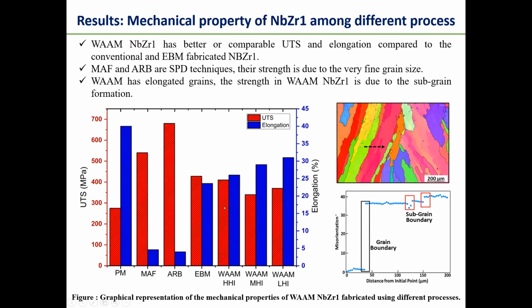So in each heat input condition, our WAAM niobium zirconium 1 has much comparable or better yield, UTS and elongation compared to PM and EBM, powder metallurgy and electron beam melting, niobium zirconium 1. But with respect to multi-axial forging and accumulated roll bonding, our yield stress is much lower. But both of these are SPD, or severe plastic deformation, techniques. They have very fine grain size. Their strength comes at the expense of their ductility, so we can say that WAAM niobium zirconium 1 has potential for use.